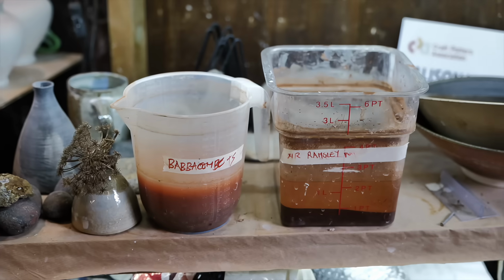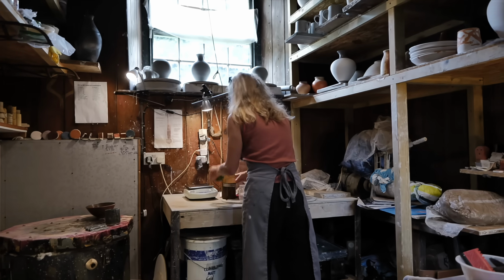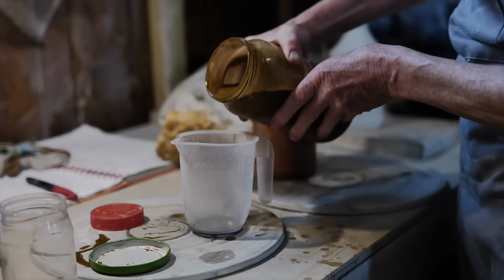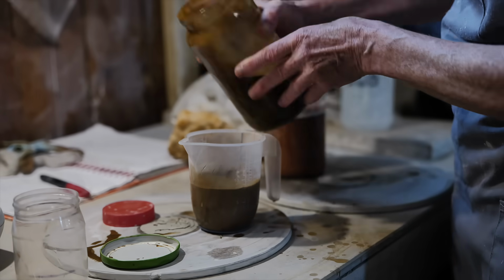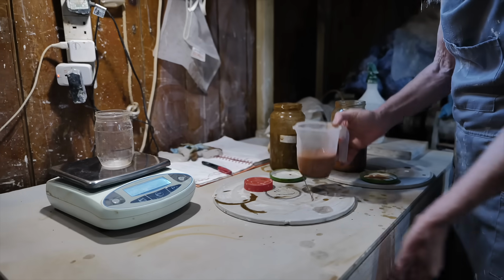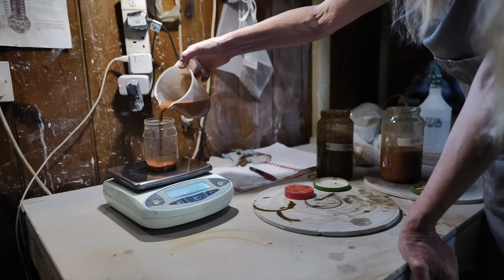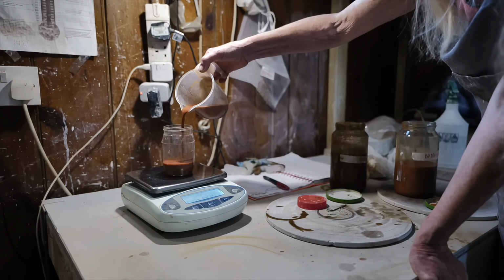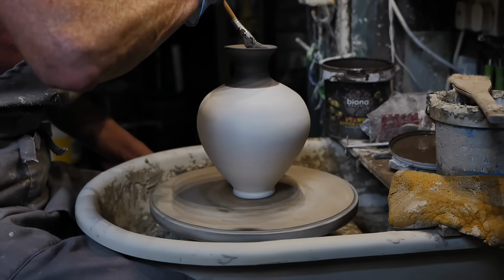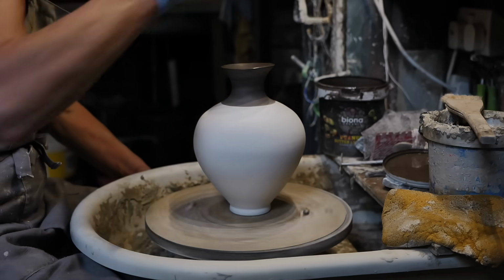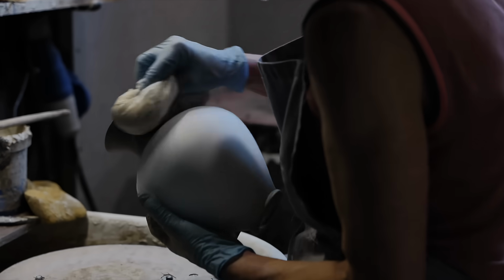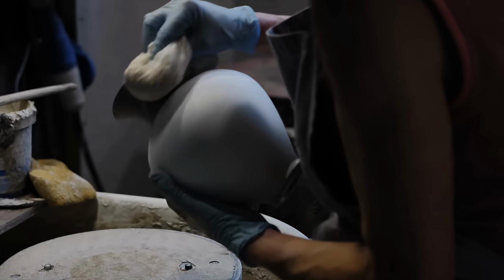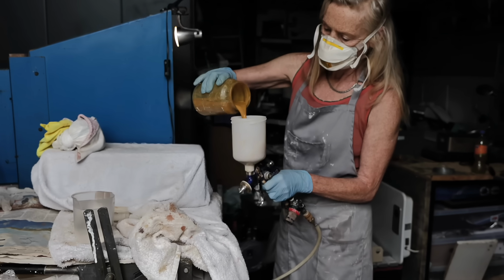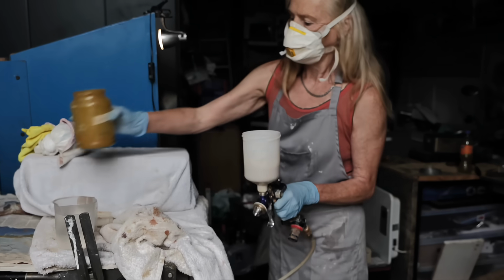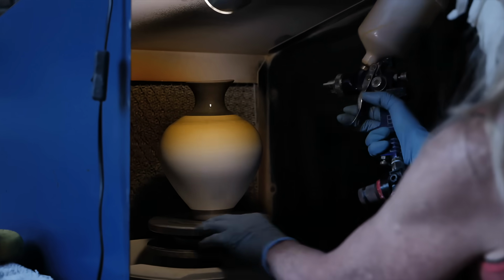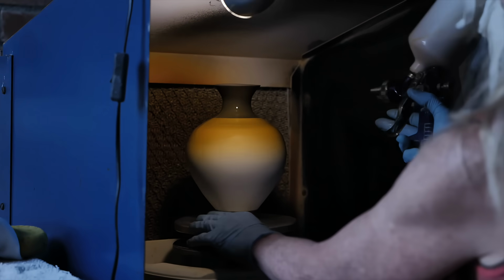Terra sigillata is a general term for ancient Roman pottery with a glossy surface. It's roughly translated as sealed earth, but the meaning of terra sigillata is clay bearing little images. I make my terra sigillata from the wild clays of Devon and one from Cornwall. Some of them are granite clays, some of them are ball clays, and it's an ongoing, very exciting and inspiring process because there's mud everywhere. Once I've added the blue-black terra sigillata on the neck and the foot, I spray layers of different Devon terra sigillata clays onto the pot.